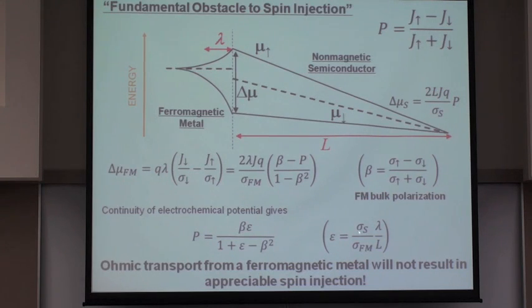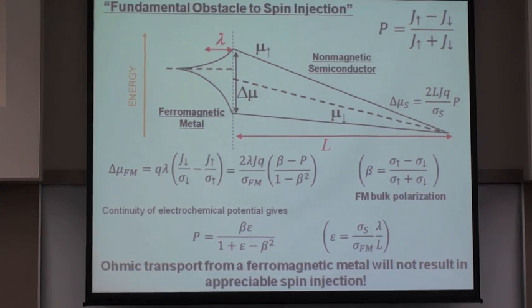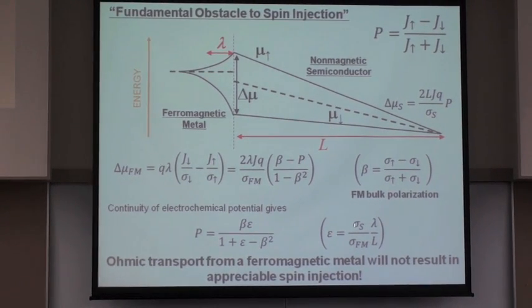Now, what's important here is that, as I said before, the conductivity of a semiconductor is much smaller than the typical metals. And so this ratio here between the conductivity is very small. Not only that, it's also proportional to the ratio in the length scales. And because, at least in silicon, the spin lifetime is very long, the transport length scale in the semiconductor is also very long. And so this ratio is, once again, very much smaller than unity. So this epsilon is a very small quantity.